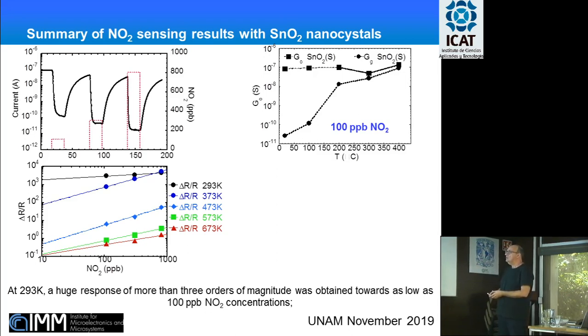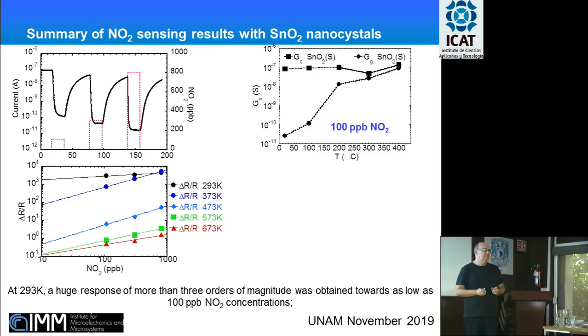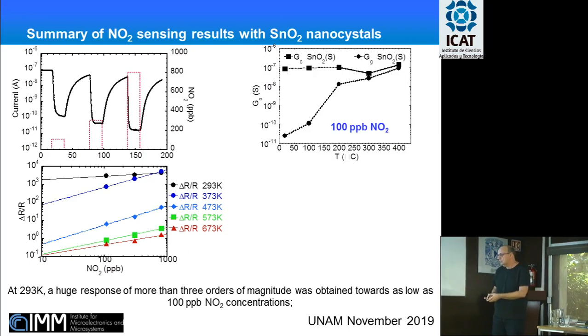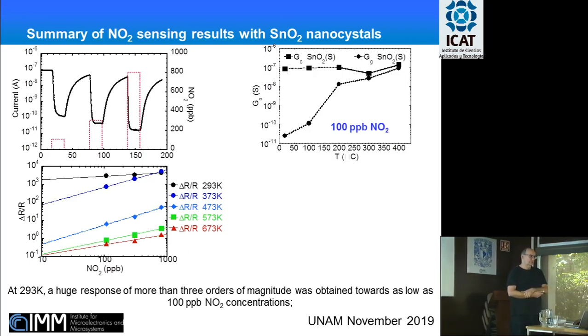This is a summary of the nitrogen dioxide sensing results with tin oxide nanocrystals. And we can see that with these materials, it was possible to obtain a response ranging over almost 3 orders of magnitude down to as low as 100 ppb concentration of nitrogen dioxide, which means that electrical conductance in these devices decreased by at least 1,000 times when exposed to such a low concentration as 100 ppb or even less of nitrogen dioxide, which is a result not easily obtained with other oxides. So it was possible to prepare tin oxide nanocrystals, very tiny nanocrystals. They remained tiny even after the treatment, for reasons that I don't have the time to explain now. And the resulting devices were providing this enormous response to very low NO2 concentrations.